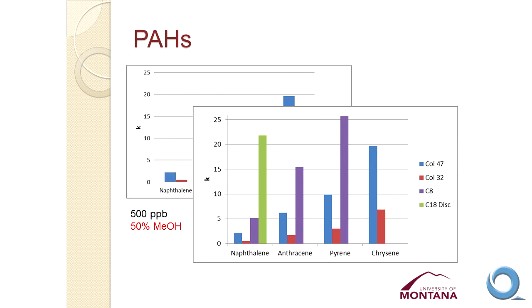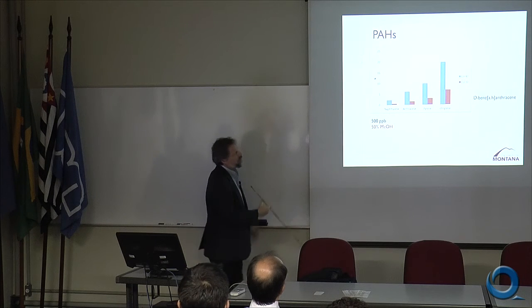We continued this with polynuclear aromatic hydrocarbons. The retention of these PAHs was too high if we did aqueous mobile phase or aqueous media. So we made all of our measurements in 50% methanol. This brought the retention factors down into the range where we could measure them. And then we looked at column 47 and column 32 again. Much more retention in column 47 than in column 32, and an increase in retention as we increase the size of these PAHs. This is 2 rings, 3 rings, 4 rings in a symmetrical structure, and 4 rings in more of a linear structure, and then 5 rings, which I haven't shown on here because the retention factors were too high to measure on column 47.